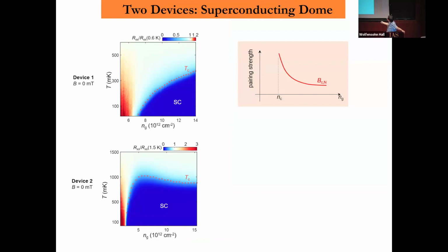Now, if this is the case, then why do we see this in the transport? It turns out that's only because of disorder, because what happened at so-called TC is only TBKT, which is very sensitive to disorder, because that's the transition induced by vortices. So using the exact same fabrication procedure, we have another device now that looks like this, where even the transport resistance shows TC now going up.